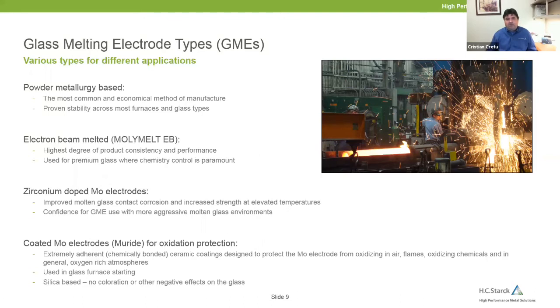We also make electron beam melted, or so-called MOLYMELT EB glass melting electrodes. These are not so common. They are typically used only on premium glass. Why? Electron beam is basically a process in which one melts molybdenum by bombarding it with several, let's say, streams of accelerated electrons. They raise the temperature of the metal to such high melting points that pretty much all the other elements, with minor exceptions, will boil and evaporate. So this is not only a melting process, it's also a purification process.